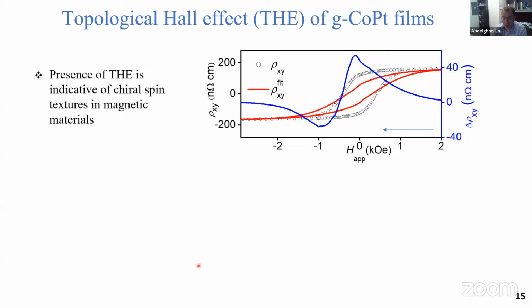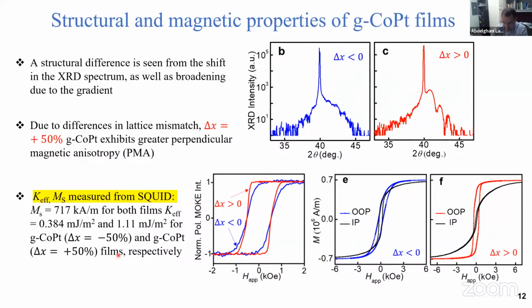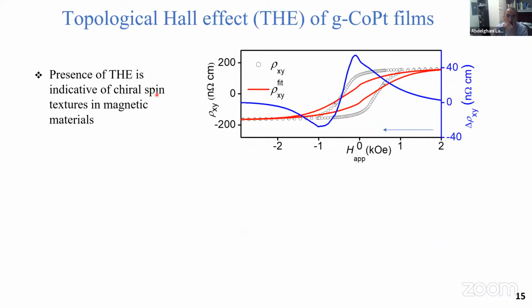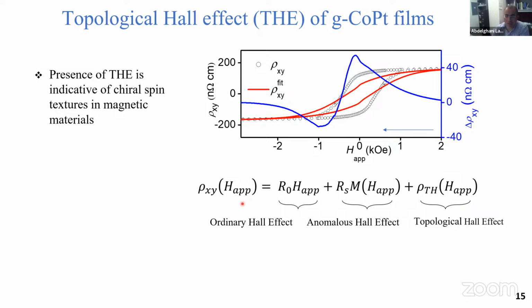After we know exactly what Ms is, and also the effective magnetic anisotropy, we used topological Hall effect. In this case, we have some devices on these films, and we try to measure the resistance. So usually we do magnetotransport measurements as well as SQUID measurements. From here, you can measure the resistance, where you have the normal ordinary Hall effect, you also get the anomalous Hall effect, and then you get the topological Hall effect. So by subtracting, usually, for example in this case, the signal from VSM or SQUID, one can get this topological Hall effect blue signal. You have a positive or negative signal depending on the applied magnetic field. And both of these, as I said, were measured using the SQUID.